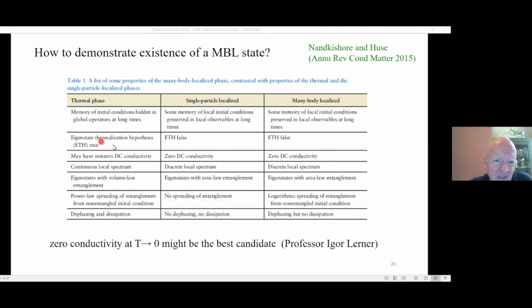If we're in the normal phase, the system comes to thermal equilibrium. If we're in the localized phase, the eigenstate thermalization hypothesis is false. System doesn't come to equilibrium. True in both cases. Discrete local spectrum for single particle localized, same for many body localized. The overlap between the single particle localized and the many body localized is actually quite large. And it looks like probably the best candidate type of measurement to do is, do we have zero conductance at finite temperatures? That's probably our best way of getting into studying this system.